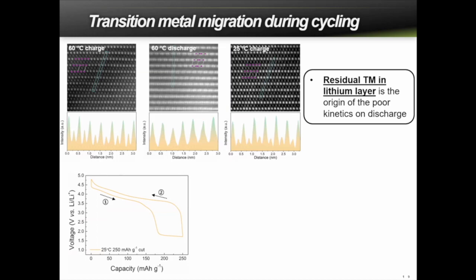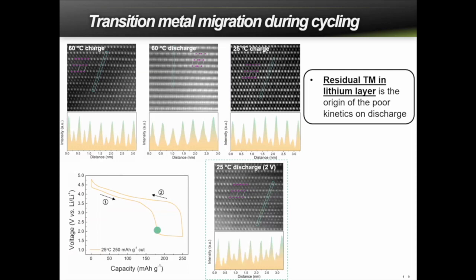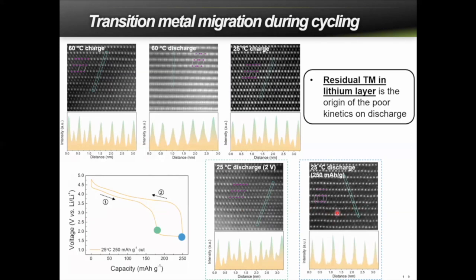On the other hand, when operated at room temperature, the transition metal ions migrate to the lithium layer upon charge, but do not completely come back with the discharge to 2 volt. Here, we see that a substantial amount of transition metal ions remain in the lithium layer, as you can see here. But interestingly, when we forced the lithium intercalation up to 250 milliamperes per gram, those transition metals are no longer observable in the lithium layer, indicating the recovery of the layered structure. So there is a clear correlation between the transition metal presence in the lithium layer and the voltage curve.